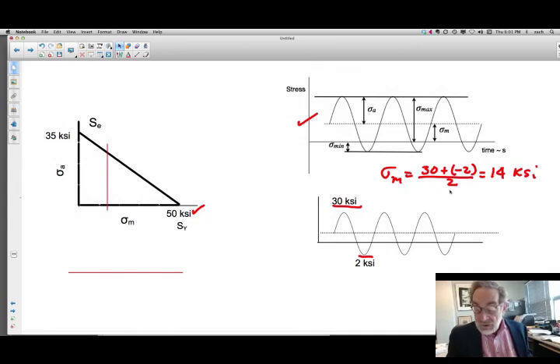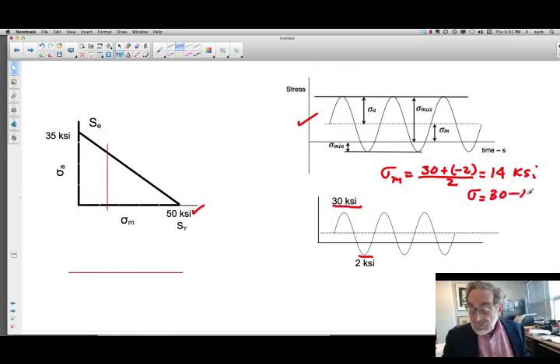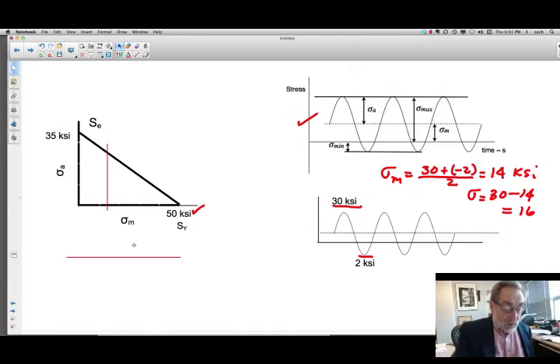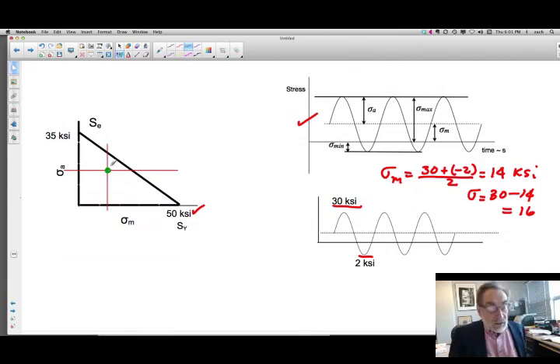So what's our alternating stress? Well that's pretty straightforward, it's 30 here minus 14 and I've got 16. So if I move my alternating stress here, here's 10, here's 16, you see I'm right here and I'm inside and I'm safe. Well the material supposedly is safe.